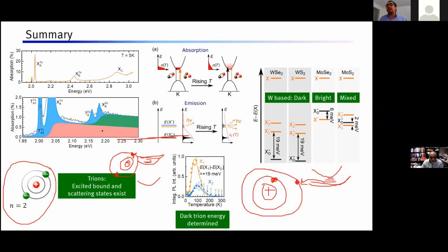However, there could be other things. For example, if the dielectric screening is reduced a lot, because in the explanation of these bound states you have epsilon at the bottom in the denominator, so if you reduce that, you can still increase the binding energy. I see. Thank you. You're welcome.